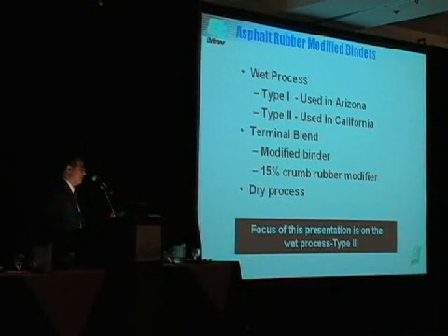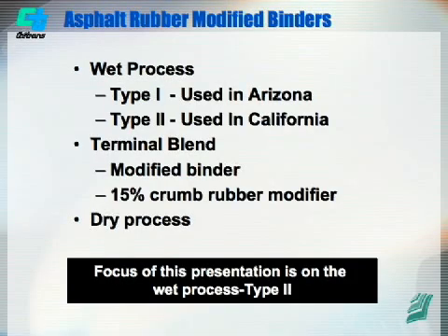Basically, there are three types of asphalt rubber binders. One is the wet process, which is the process that's been used commonly in California. Under the wet process, there are type 1 and type 2. California experimented with both. Now California is mainly using type 2 asphalt rubber binder, which uses extender oil. The state of Arizona is still using type 1, and they have experienced successful performance.